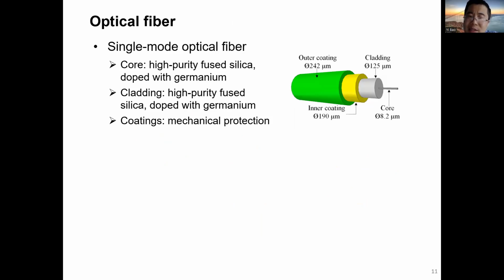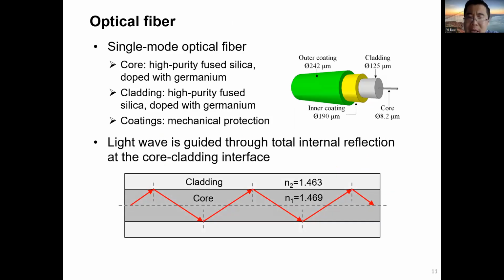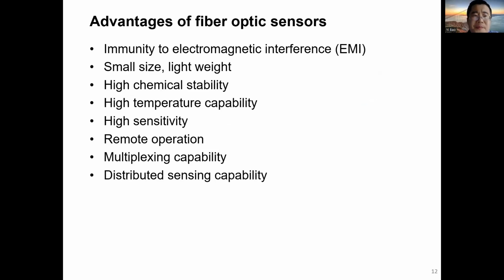Usually those coatings are made using polymer, but there are also some metal coating fibers. And for the fiber optic sensor, the light wave is guided through total internal reflection at the core-cladding interface because they have different refractive indices. And because the cladding and the core are made using high purity fused silica or glass, the light wave can propagate along the optical fiber cable for a very long distance. Therefore, we can use fiber optic sensors as both distributed sensors and transmission lines with the same cable.